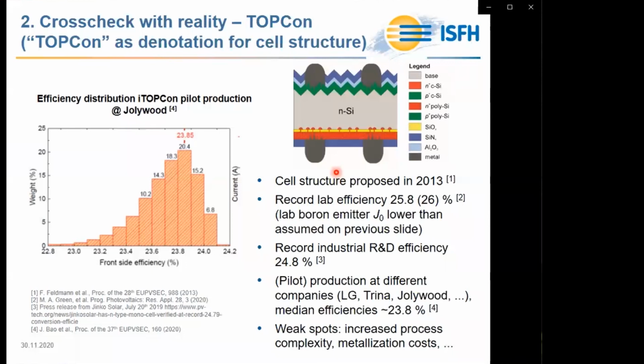However, I also would like to acknowledge that on lab scale, even higher efficiencies up to 25.8 and 26% have been achieved. That means that some components, probably in particular the boron emitter, has better properties than we assumed for our selectivity screening. The mass production has already started at some companies, or at least pilot mass production, and the median efficiencies, as reported, for example, by the company Jolywood at the PVCon conference this year, is in the range of 23.8%. Nevertheless, this technology also has some weak spots.